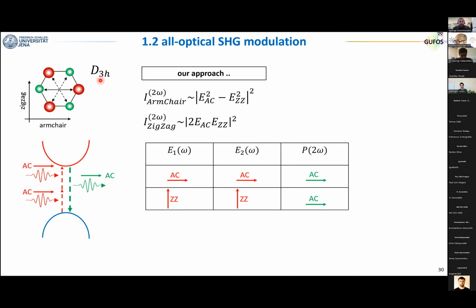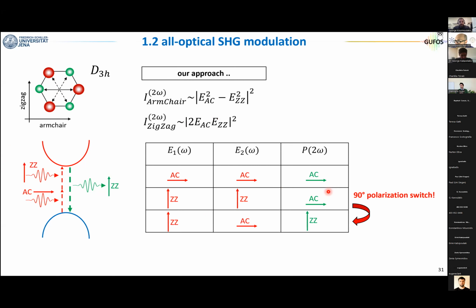Now, if you take this point group and look at what happens to the second harmonic, it turns out that if the 2 photons that contribute to your second harmonic signal are both aligned along the armchair or both aligned along the zigzag, then in both cases your second harmonic is emitted along the armchair direction. However, if you split the 2 photons that generate the second harmonic, one along armchair, one along zigzag, then your second harmonic will rotate by 90 degrees and will be emitted along the zigzag direction.